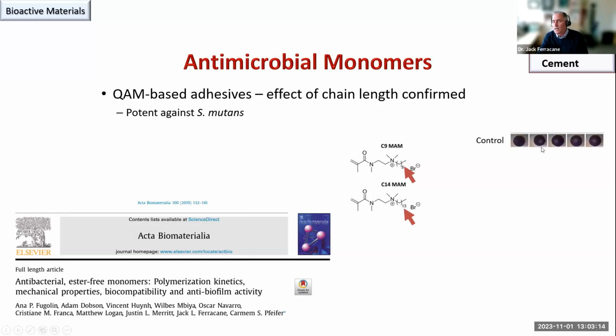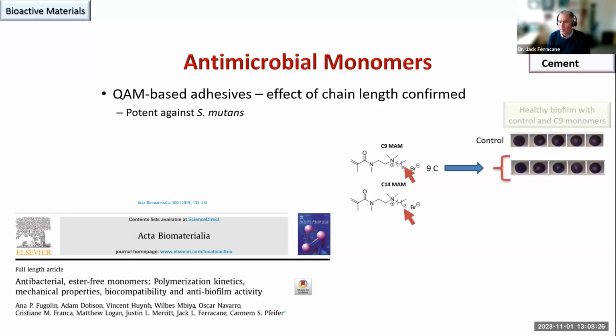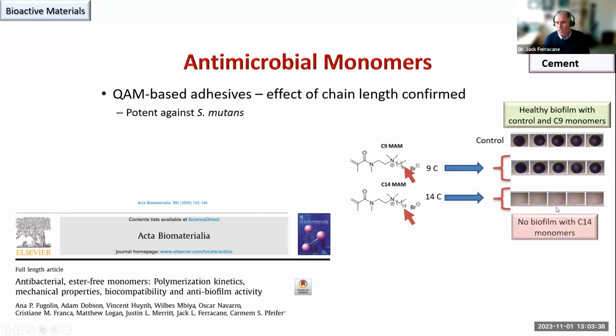violet stain, the control looks like a very nice biofilm, very nicely colored. This is with the biofilm growing on a 9-carbon molecule, and it looks just like the control. It's obviously the bacteria is not being killed. It's very healthy. And then growing on a 14-carbon chain molecule, and you see we don't even grow a biofilm. So it shows, again, the evidence for the length of the chain being very important.